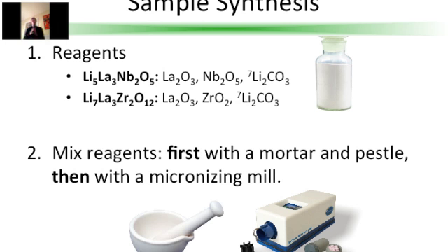For the reagents for lithium lanthanum zirconate, I used lanthanum oxide (La2O3), zirconium oxide, and lithium carbonate. For lithium lanthanum niobate, I used lanthanum oxide (La2O3) as well, niobium oxide (Nb2O5), and also lithium carbonate.